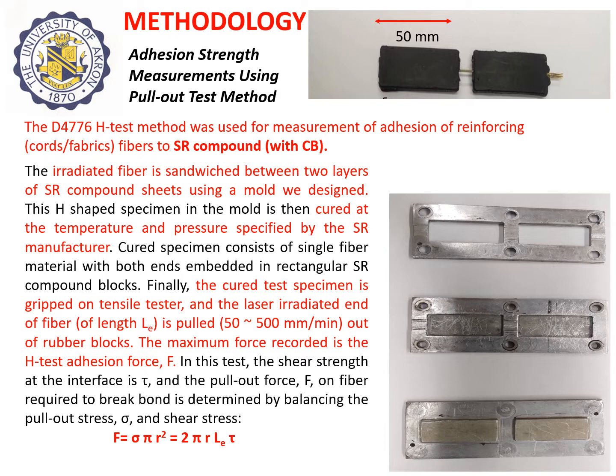We used the ASTM D4776 H-test method as the pull-out test for the measurement of adhesion. The specimens were prepared by using the molds that we machined in-house. The molds are shown on the right-hand side here. The cavities are filled with the compound, and the cord is laid over these two cavities. One side has the embedded length, and on the other side the cord goes through that rectangular section. And the resulting cured specimen is shown on the upper right.